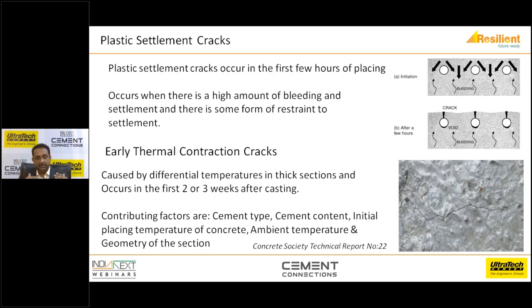If you can imagine a 2-meter thick raft and you're pouring all that together, then after the concrete is over, the temperature at the core is definitely much higher than the temperature on the surface, because the temperature at the surface can dissipate into the atmosphere very quickly, and then the temperature at the core is hot. If your temperature differential between the core and the surface is more than 25 degrees, of course, depending upon the aggregate properties, then there is a vulnerability for the concrete to crack.